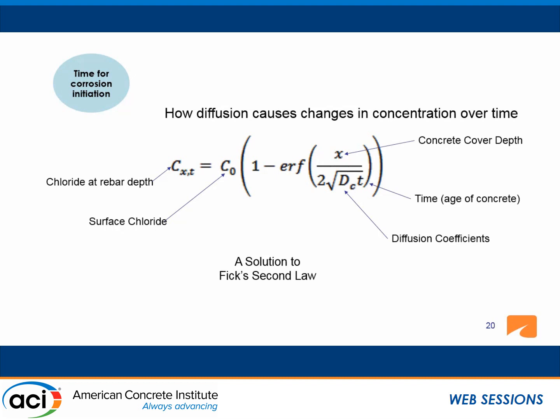The input parameters we need are the chloride at rebar depth, the surface chloride, the diffusion coefficients, the age of concrete, and the concrete cover depth. We also need the chloride threshold at corrosion initiation, which we have found to be not just a single value, but more like a distribution. We used a simple triangular distribution based on our previous studies.